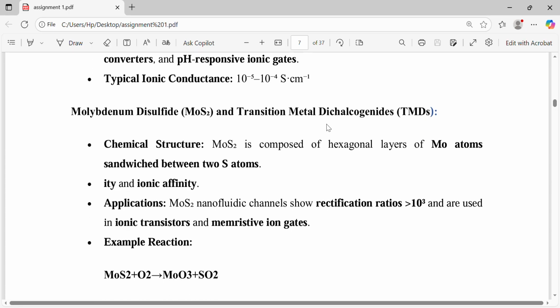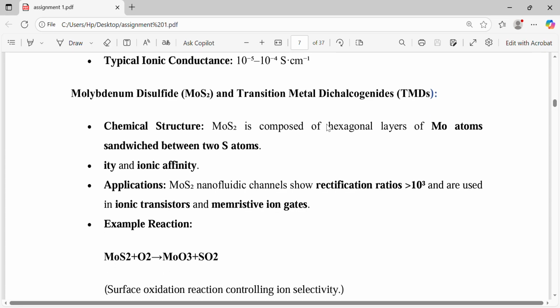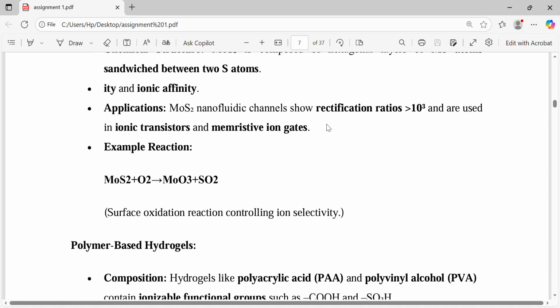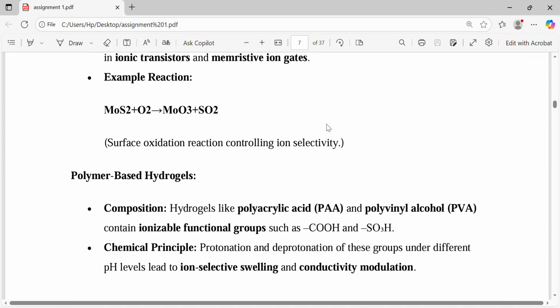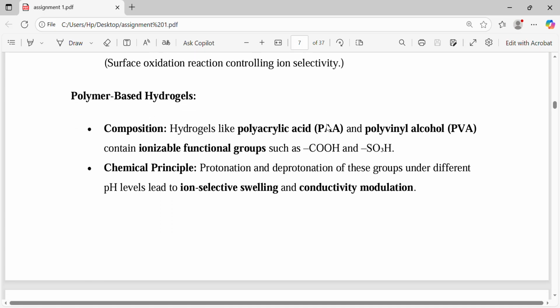Molybdenum disulfide and transition metal dichalcogenides. Chemical structure: MoS2 is composed of hexagonal layers of Mo atoms sandwiched between two sulfur atoms, with ionic affinity. Applications: MoS2 nanofluidic channels show rectification ratios of 10 to the power 3 and are used in ionic transistors and memristive ion gates. Example: MoS2 plus O2 yields MoO3 plus SO2. Surface oxidation reaction controlling ion selectivity.